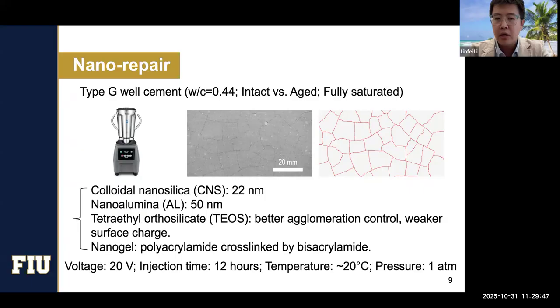These include colloidal nanosilica with a 22 nanometer diameter, and nanoalumina. TEOS is another one, what we call a precursor of colloidal nanosilica. It has better agglomeration control because it does not form particles immediately, but it's a trade-off: it has a weaker surface charge. And the other one is an organic nanoparticle called nanogel, which uses polyacrylamide cross-linked with bisacrylamide. So we have four different types, and we just play with them to see which one shows the best performance.